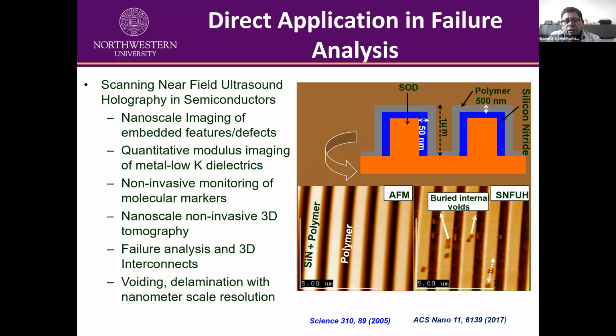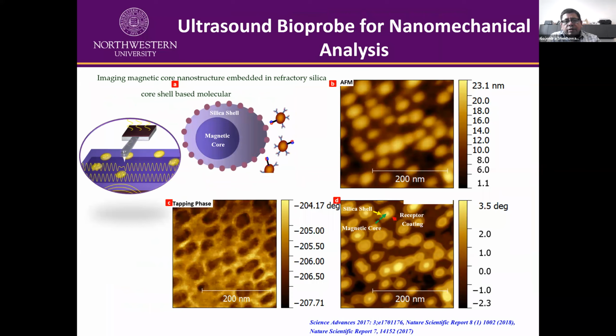How much depth you can go depends on the type of the acoustic waves that you use. If you oscillate them at a high frequency, you can go much deeper. But we haven't done that much research on how deep we can go. But the latest in this category, we use nanoparticles with a magnetic core. If you're familiar, people use TEM to see the core embedded in the silica. Okay, so you have to use the TEM. But here, the top right is basically a typical tapping mode image of these silica particles, which have a magnetic core. You cannot see those magnetic cores.